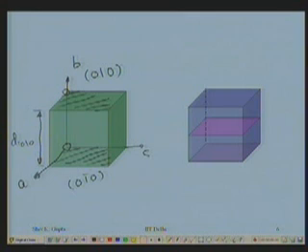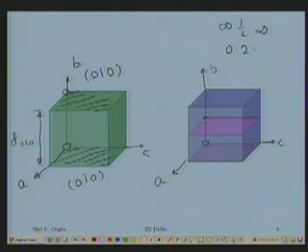let us call that D010. Right. Now, let us locate in a unit cell, same unit cell maybe, let us name this as C here, A here and B there. This plane in the middle, if I start with this origin, it is parallel to A, parallel to C and makes an intercept of half on B. So, intercepts are infinity, half and infinity. Reciprocals of these intercepts would become 0, 2, 0. So, this pink plane here is 020.